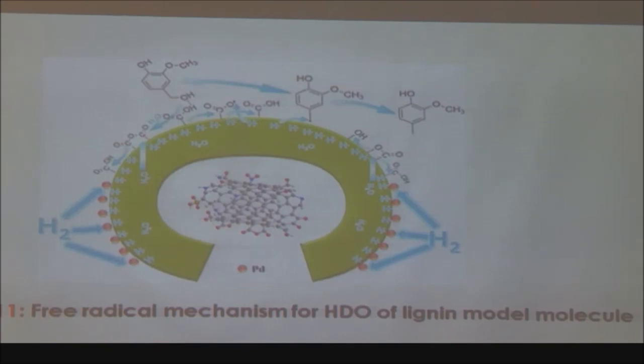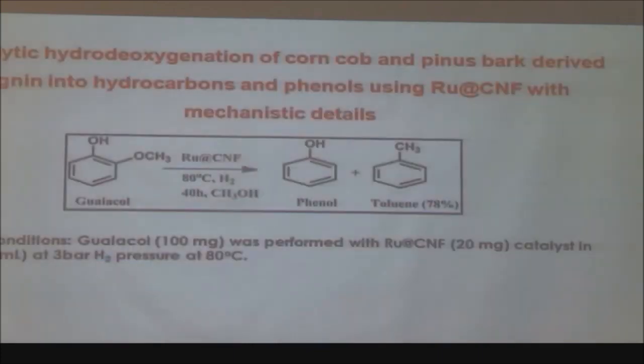But again, we fail to show that it is 100% radical, because it should be zero, but we never get a 0% conversion, even when we use an excess of the radical quencher. So what does it mean? That both the things are there. Because if metal ion is there and you are not able to remove that, you are unable to stop that ionic mechanism. So whatever work we have done again leads to the indication that both the mechanisms are prevailing on the catalyst surface, the ionic mechanism as well as the free radical mechanism.